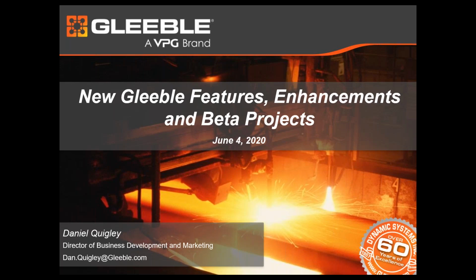One question we do occasionally get, because we can melt in the HDS V40, which is a direct melting and casting simulator, and we also get this in some of the melting simulations we offer in the 3800 and 3500, is: can we alloy directly in the Gleeble? The answer to that question is kind of. We can obviously add some elemental wires or powders either onto the HDS V40 sample or into the quartz crucible in the melting setup in the 3500 and 3800. The problem is that we don't have a way to control exactly the size of that melt zone. So it would be a little bit of a shotgun approach.